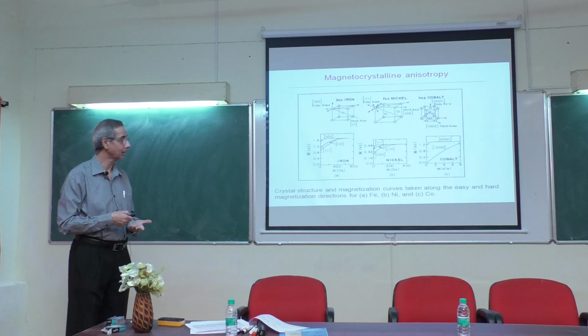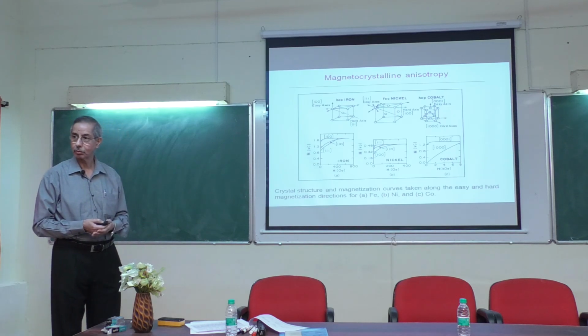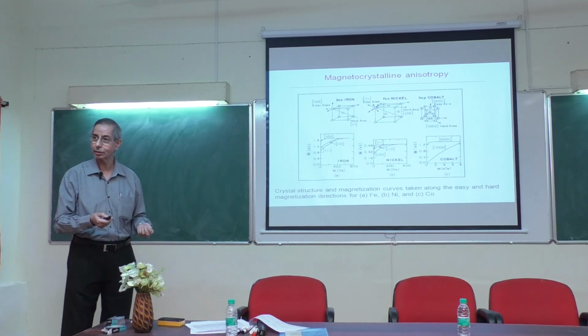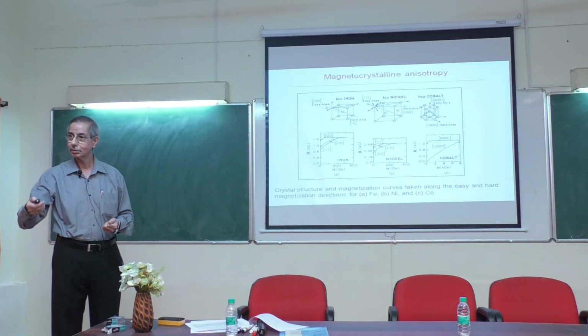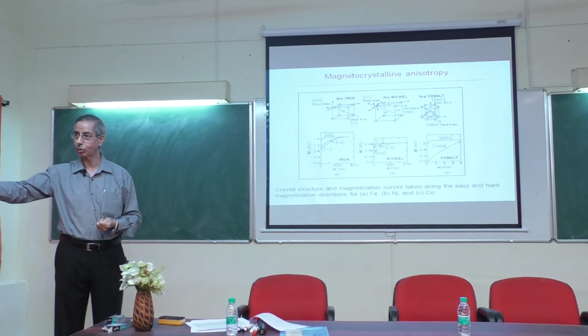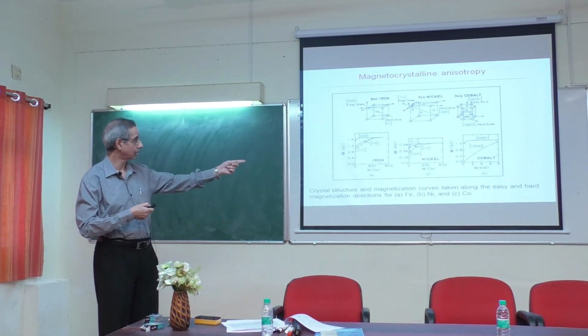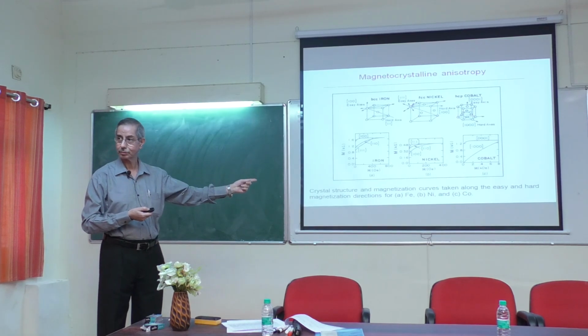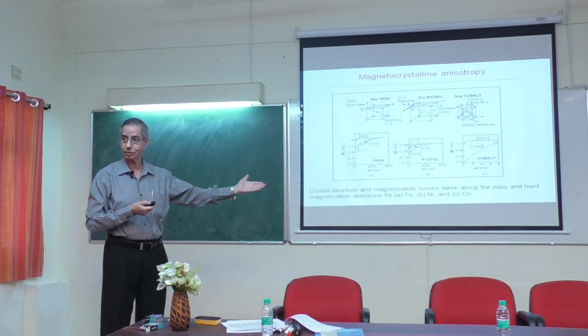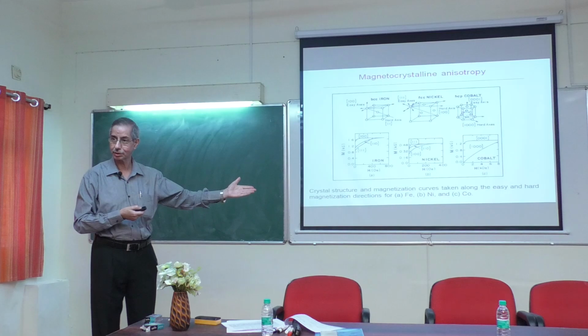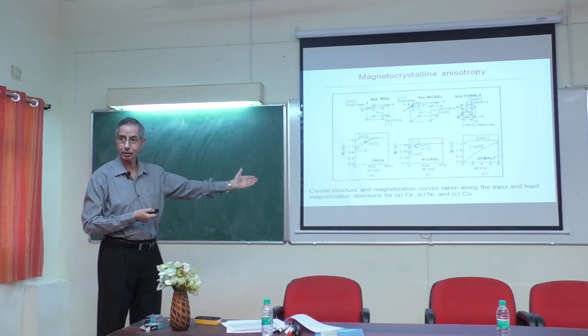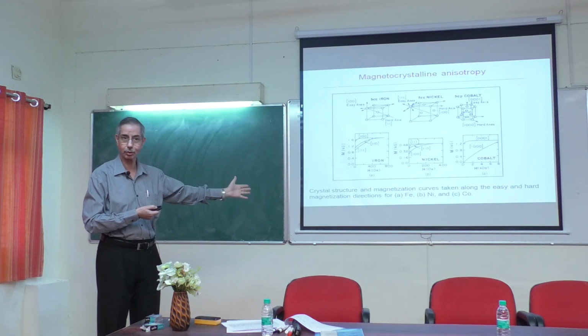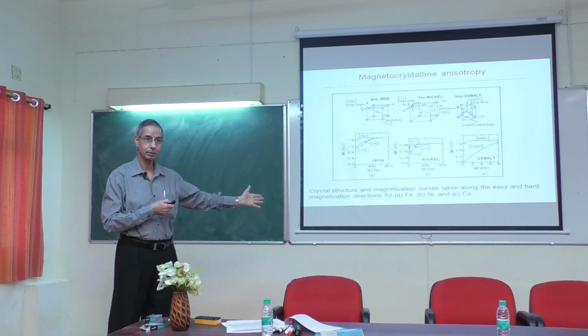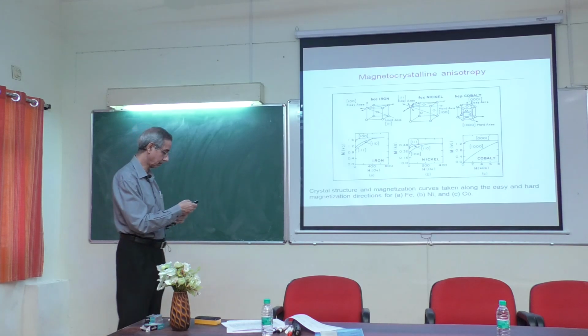So what does it mean? It means the work done by the field goes on increasing as you go from nickel to iron and then cobalt. Cobalt is an order of magnitude higher, as you see. You need a few kilo-Oersteds to get to saturation, whereas here it is tens, hundreds of Oersteds or tens of Oersteds, right? So that is the one important point.